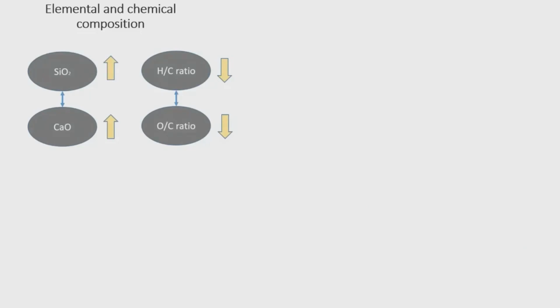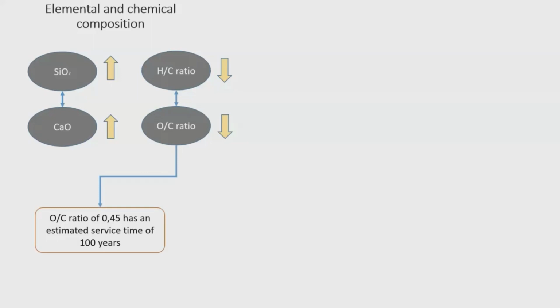Another important aspect of biochar, which is worth mentioning, is its HC ratio and its OC ratio. Its hydrogen to carbon ratio and its oxygen to carbon ratio. We expect low values for these two ratios since these describe the stability and longevity of biochar inside the cementitious matrix. According to research literature, an OC ratio of 0.45 has an estimated service time of 100 years in an inert nature and without degrading itself.